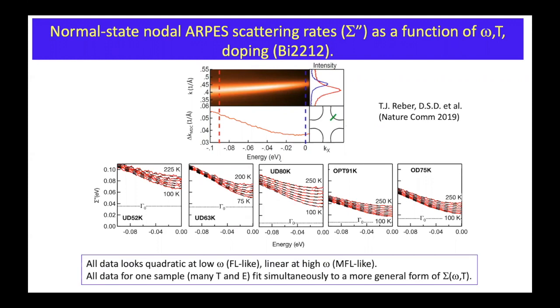So this is an ARPES measurement along this green cut here. So energy versus k, here's the Fermi energy. And the dispersion in this case would come way down here as some sort of parabolic band. This is raw data. And in this case, it's fair for me to use just MDCs, and that's because the dispersion is very linear. I won't do the 2D spectroscopy that I'll talk about after this.